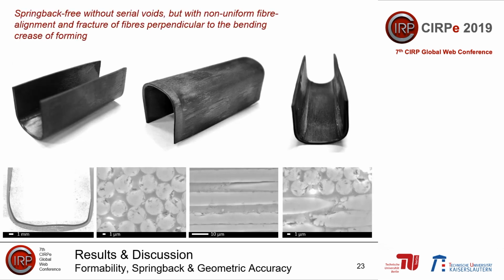So we managed to produce springback-free parts. If we look under the microscope, however, we can see some geometric inaccuracies. So we have areas of thinning in the corners, we have waviness to the surface profile, but these defects are probably the result of insufficient die design and refinement rather than problems with the process itself. However, here we can see non-uniform fibre alignment. Here we can see fibre fracture perpendicular to the bending crease of forming. These are more important and severe forming defects.